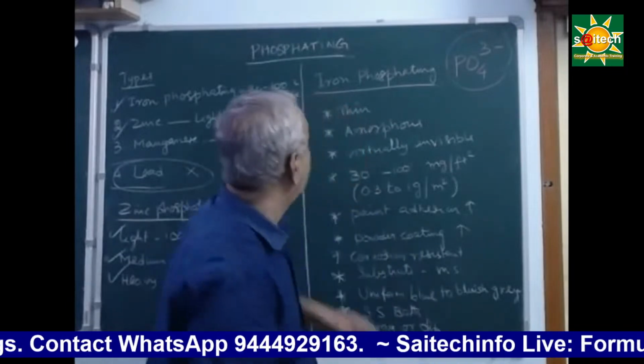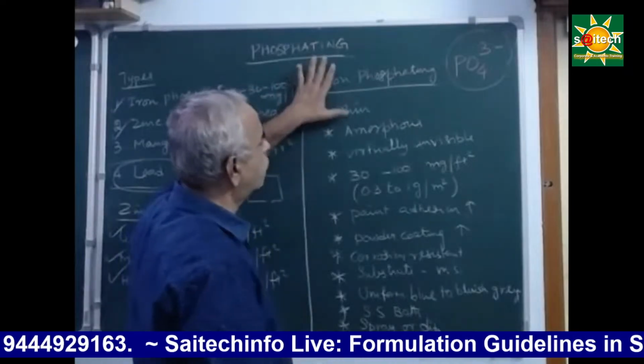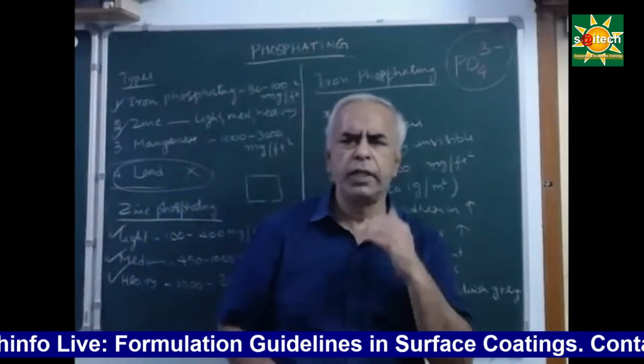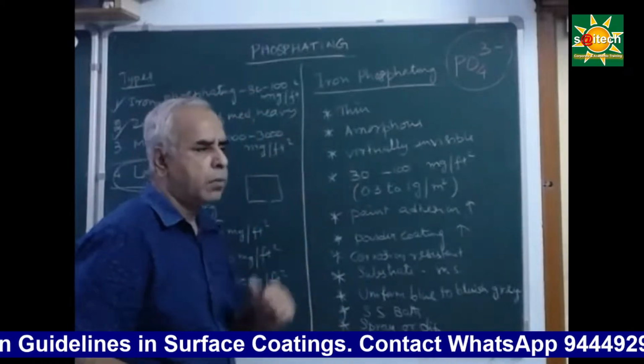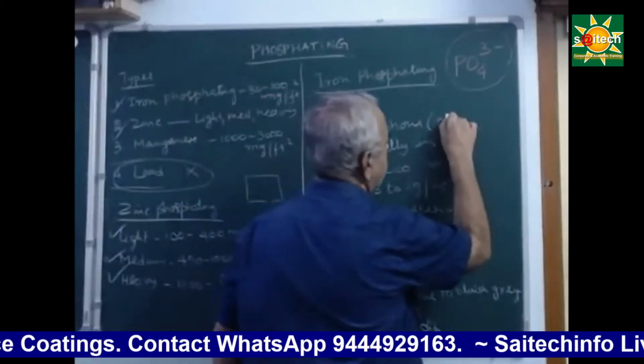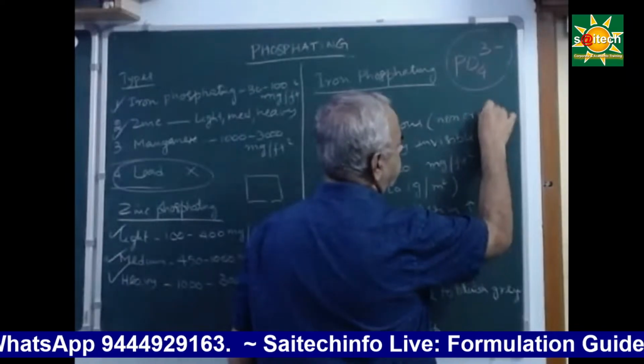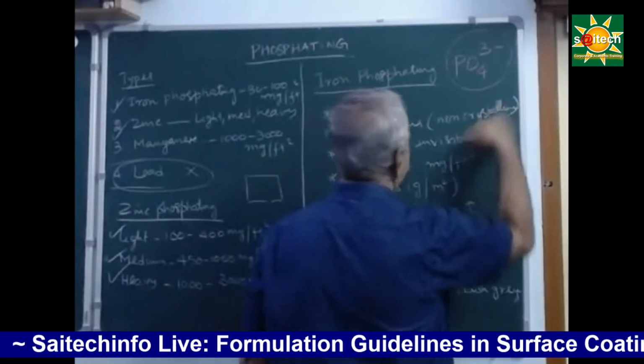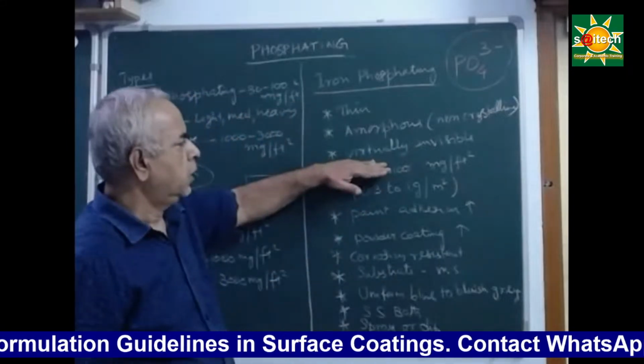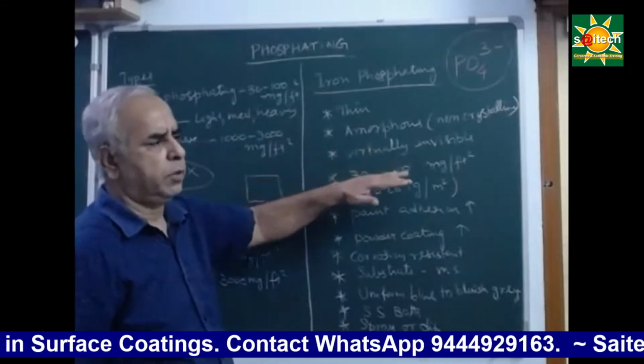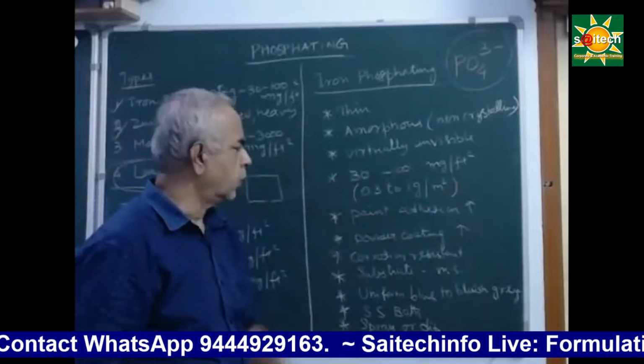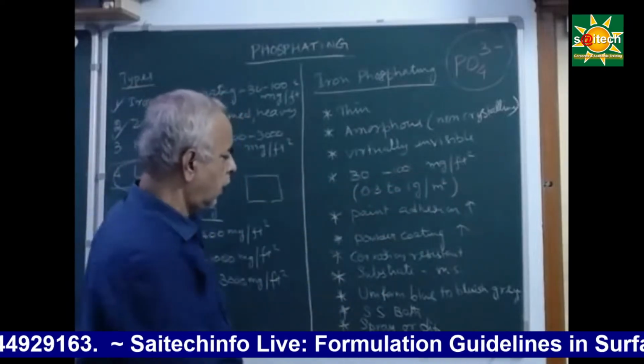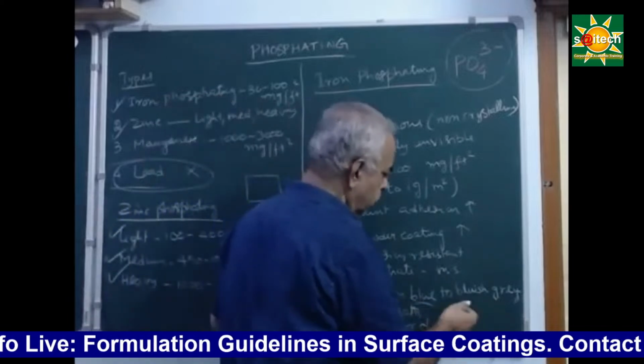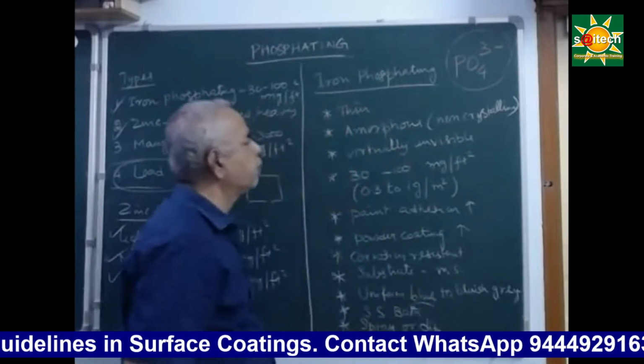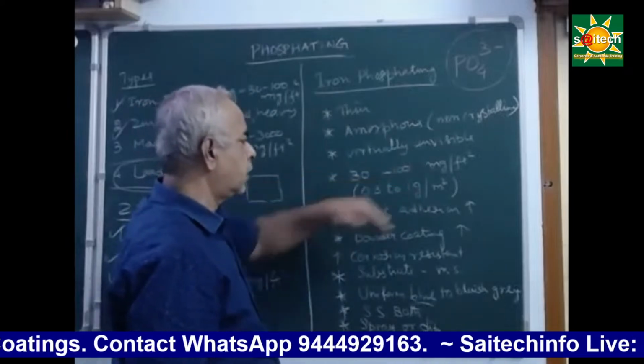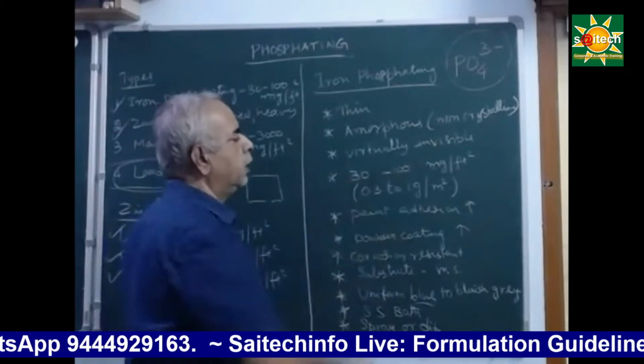Now let us focus on iron phosphating. Iron phosphating is actually a very thin coating. It is amorphous, which means non-crystalline. It is almost virtually invisible. You cannot see the coating formation so clearly, even though the color may be uniform iridescent blue, or bluish gray. The coating weight ranges from 30 to 100 milligram per square foot.